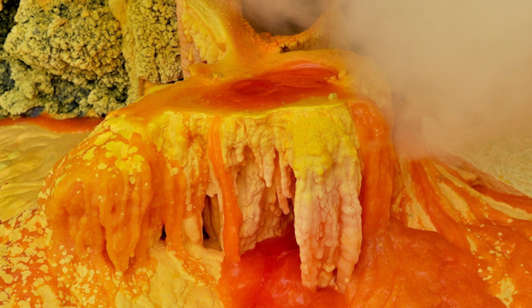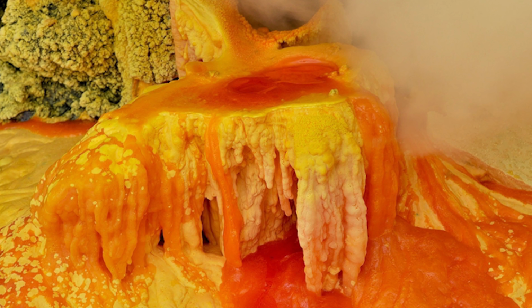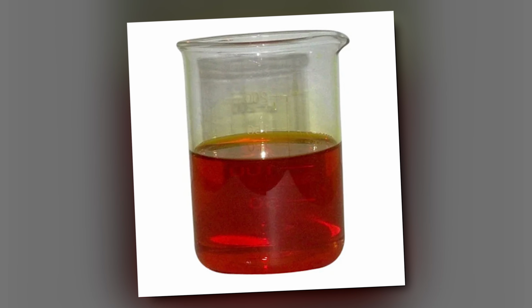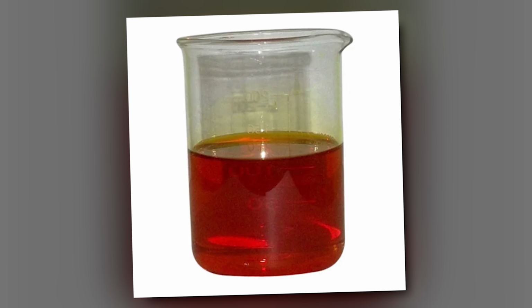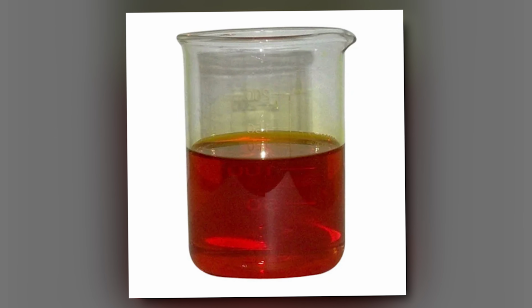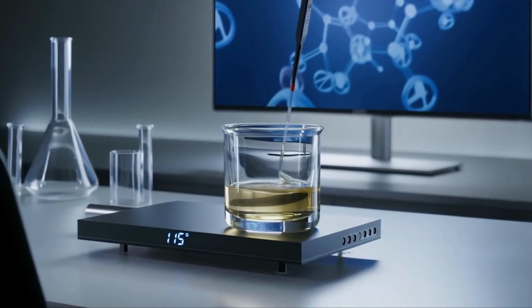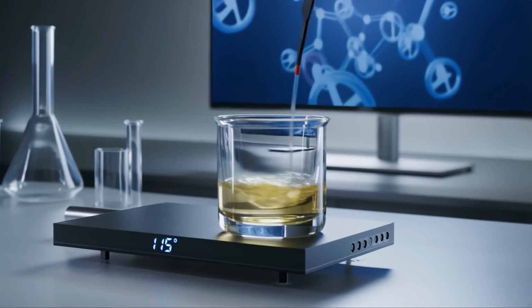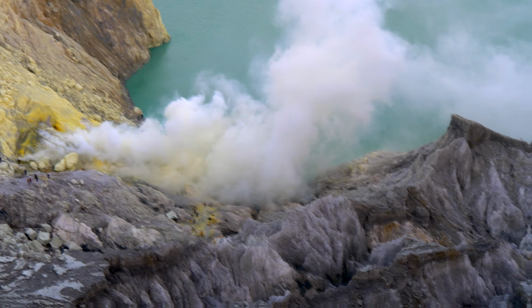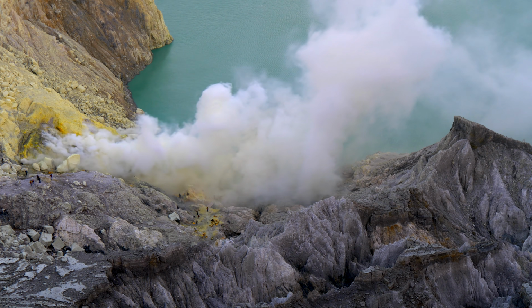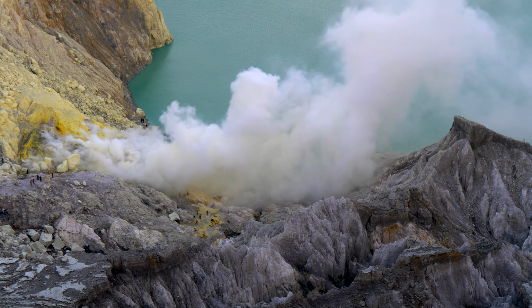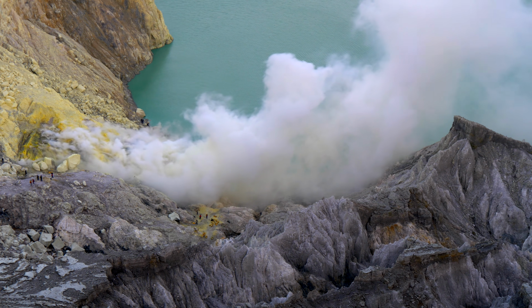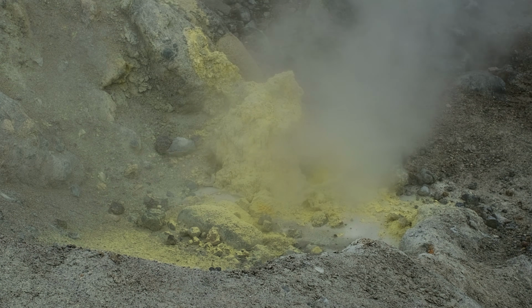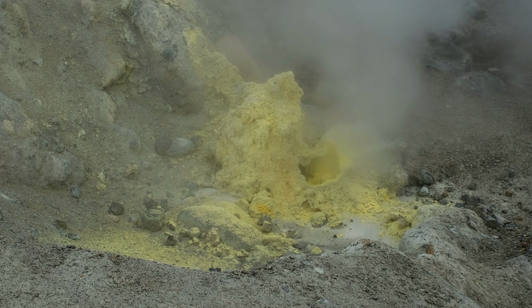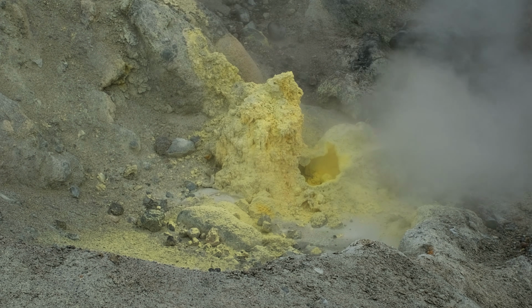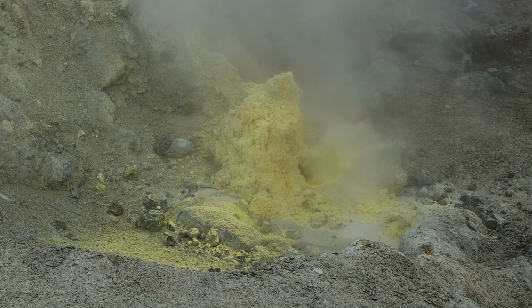Chemically, the behavior is understood as polymerization in the liquid state. The process is fully reversible. If the liquid is cooled back down, the chains gradually revert to S8 rings, and the liquid returns to its thin yellow appearance before eventually solidifying again. If it's heated even further, above 300 degrees Celsius, it undergoes yet another change. The long chains begin to break apart again due to thermal stress. As they depolymerize, the viscosity drops back down. Eventually, if you push it above 445 Celsius, sulfur begins to boil.